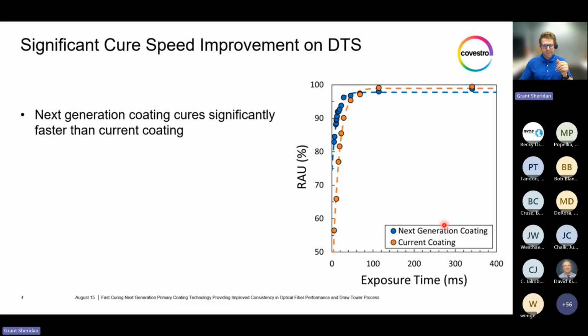So shown here is the cure speed of the next generation coating in blue compared to our current coating technology in orange versus exposure time. The RAU represents the reacted acrylate unsaturation, which is essentially just the double bond conversion measured via FTIR. So the first thing that I would say pops off the page is just how much faster this next generation coating cures compared to our current coating technology.